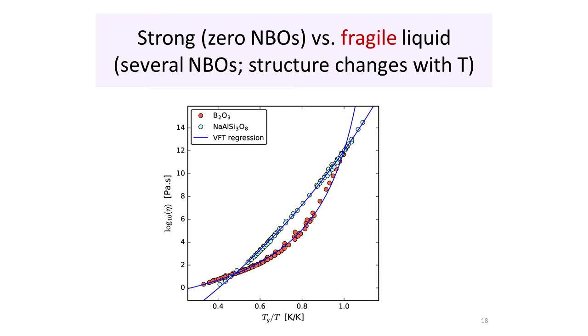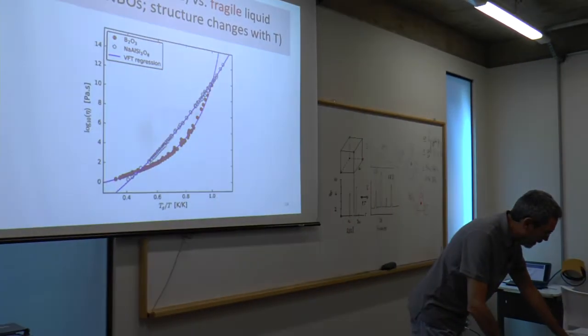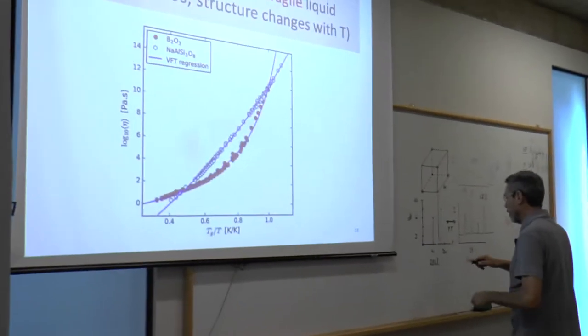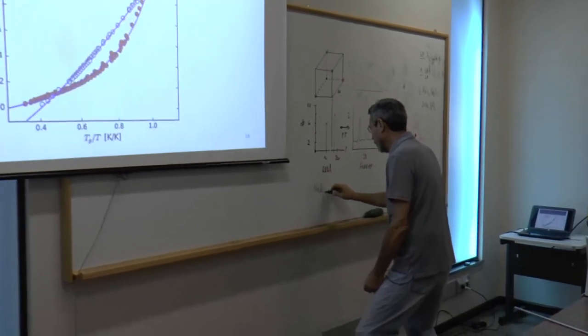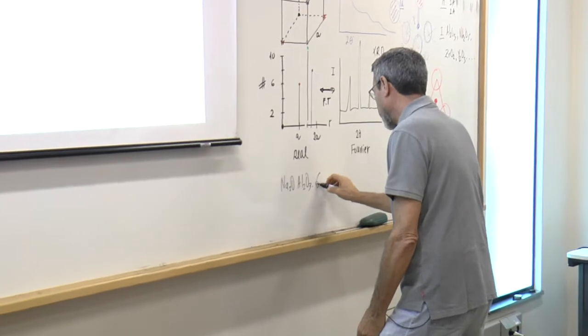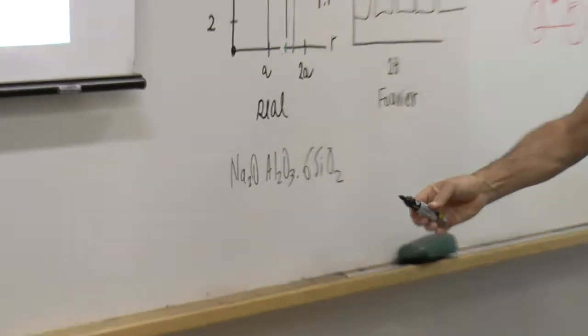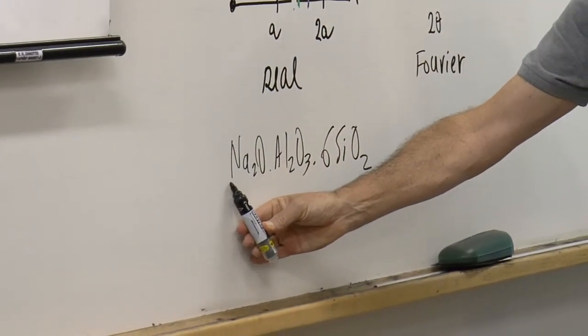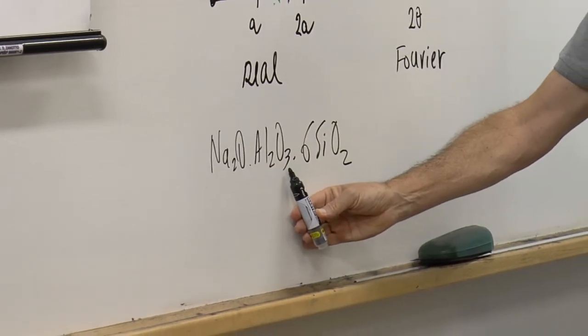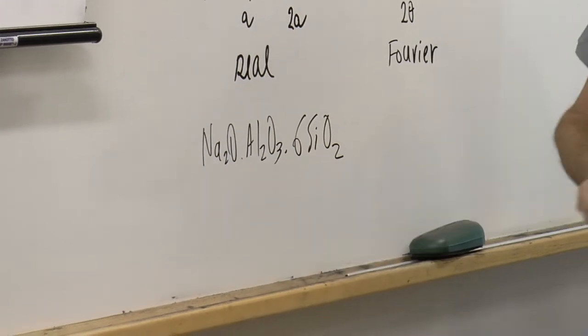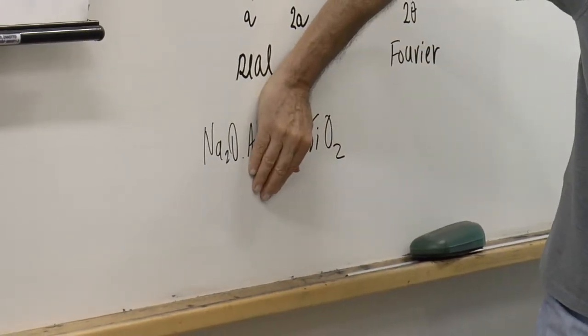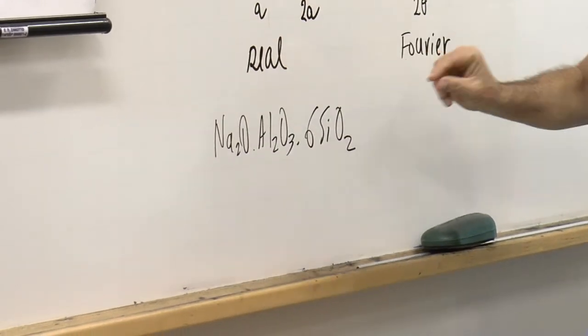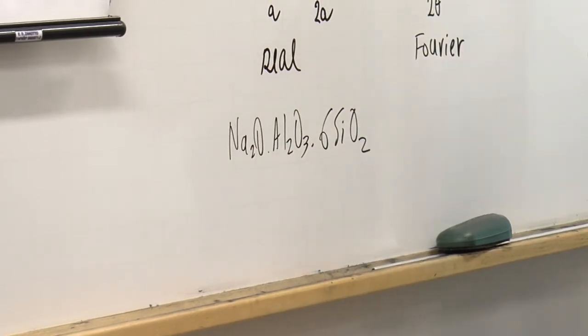The net effect is that this glass is sodium, aluminum, silicate. It's albite. So albite has the composition of Na2O, Al2O3, 6 SiO2. See what happens here? It's 1 mole of sodium oxide, 1 mole of alumina, all non-bridging oxygens that existed in this glass. If we had sodium hexasilicate, you have a lot of non-bridging oxygens. If you add alumina, exactly 1 to 1 mole, all the non-bridging oxygens are recovered,